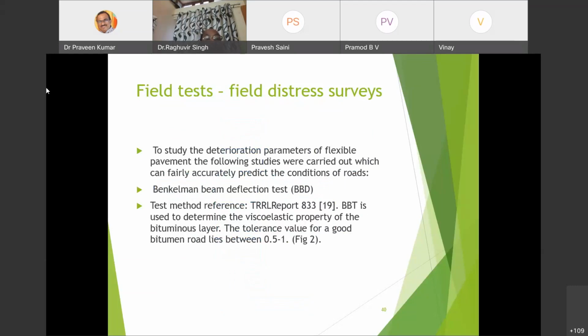So the Benkelman beam deflection survey test was conducted on that one. The test was performed as per TRRL Report 833, and the BBD is used to determine the viscoelastic property of the bituminous layers. The tolerance value of a good bitumen road lies between 0.5 to 1%.